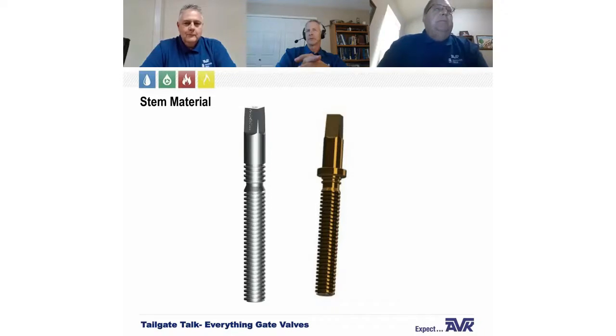Are they the same? The temperature ratings are the same, and the maximum temperature rating for the AVK gate valve is 160 degrees. It's primarily because past 160 degrees, the bond between the ductile iron and the rubber will start to degrade. And the hotter it gets, the faster it degrades. So like 170 degrees, they'll probably last you 5 years, 180 degrees a year. But that's never been tested, so don't take it to the bank. So our maximum long life operating temperature for AVK gate valve is 160. And it's a good question, by the way, Stephen.